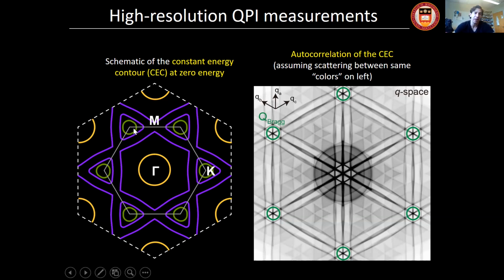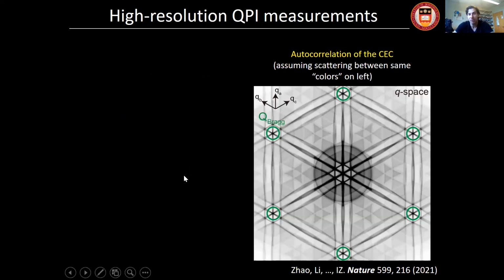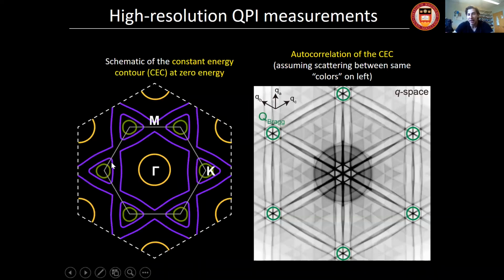So we autocorrelate everything within the first and the second Brillouin zone and just assume scattering between the like colors. So we just use a very simplified model to capture basic features of what one might see. And what's interesting is that you see this kind of triple stripe feature along all three directions that come from scattering, oops, give it away a little bit, from scattering between different parallel sheets here.